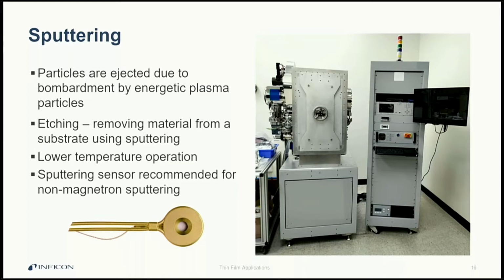With sputtering applications not relying on a heated source material, the operation can take place at much lower temperatures. And this is where you're going to see a lot of those plastics and temperature sensitive substrates get used. A sputtering application may be required with a sputtering sensor if you're using a non-magnetron sputtering application. And that's because the electrons would hit the sensor otherwise, but with a sputtering sensor, which has a permanent magnet, it's able to deflect a lot of those incoming stray electrons.